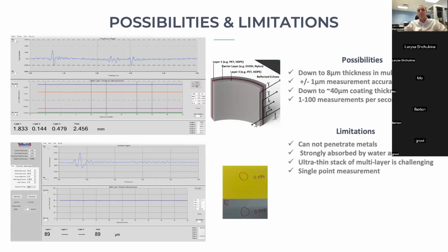When it comes to coating measurement, for example, a coating on a metallic substrate or on a non-metallic substrate, a lot of other techniques have limitations to measure a coating on a non-metallic. With terahertz time of flight measurement, you can easily do that. Coating thickness down to about 40 micron is easily doable.